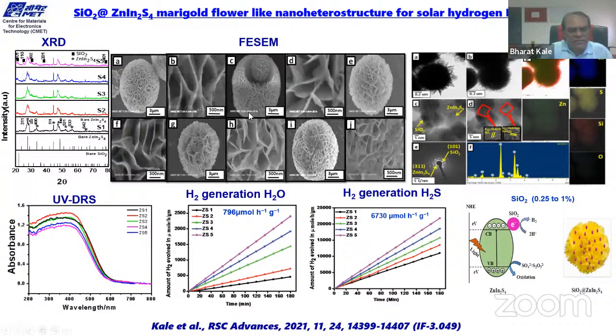In one of our RSC Advances papers we have specifically written how these petal-like structures form, and how these petals are aligned and form the flower-like structure. These structures are quite porous. You see the overall shape is in microns, but the petals are very thin, a few nanometers in thickness. One petal may have 500 nanometer length, or 600 nanometer, or 1 micron length, but the thickness is 1, 2, 3 nanometers. So the aspect ratio is much higher in this case, and this aspect ratio really helps in giving more surface area for the reactions.